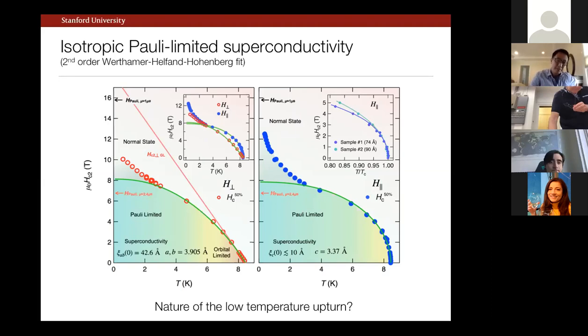What is obviously an intriguing feature, that at present we don't feel like we can definitively assign, is this low temperature upturn that you see in both directions. Okay. So I can just say in words that we've been thinking about various possibilities. Let me list a few. One is that we can unconstrain the WHH fit to allow for a first order crossover. And so this might be associated with a second order to first order crossover. You could think in terms of multi-band superconductivity, perhaps. Qualitatively, it doesn't really seem likely, but the possibility of having a second band condensing.